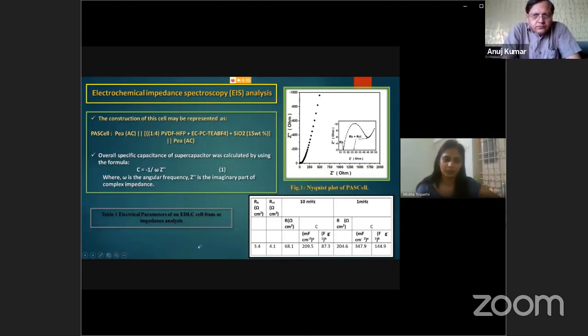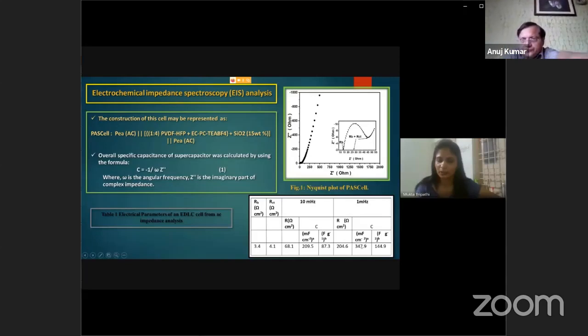So for impedance, you can see this is the impedance plot, and these are the parameters we obtained from it. Here the bulk resistance as well as charge transfer resistance, and at 1 millihertz that particular capacitance has been obtained, that is 347.9 millifarad per centimeter square, as well as in the form of the mass, that is 144.9. That capacitance has been calculated using this formula.